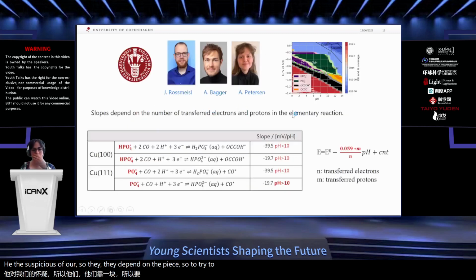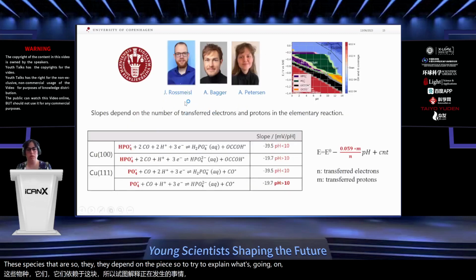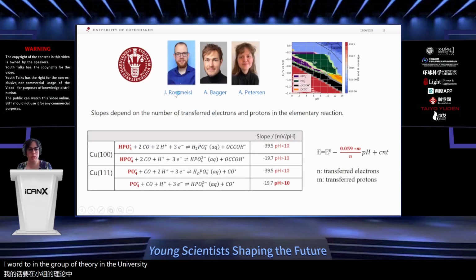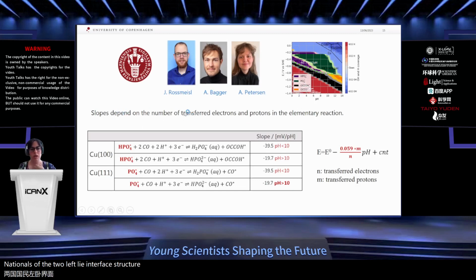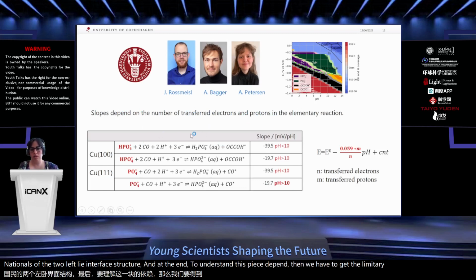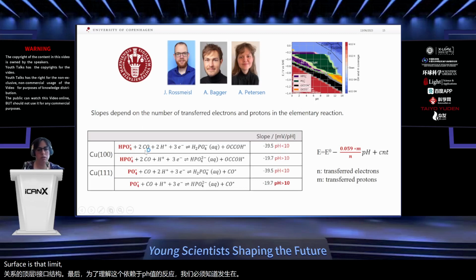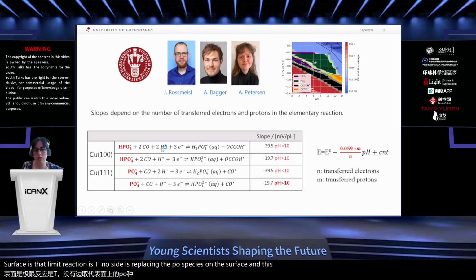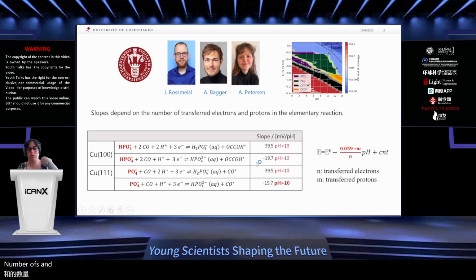So to try to explain what's going on, our collaborators in the theory group at the University of Copenhagen, Alexander Bagger and Amanda Petersen from Jan Rossmeisl's group, made simulations of the copper electrolyte interface structure. And at the end, to understand this pH dependence, we have to look at the elementary reaction that is happening on the surface. The elementary reaction is carbon monoxide replacing the phosphate species on the surface, and this reaction involves the transfer of protons and electrons. A specific number of protons and electrons are transferred, and this number is what determines the pH dependence.